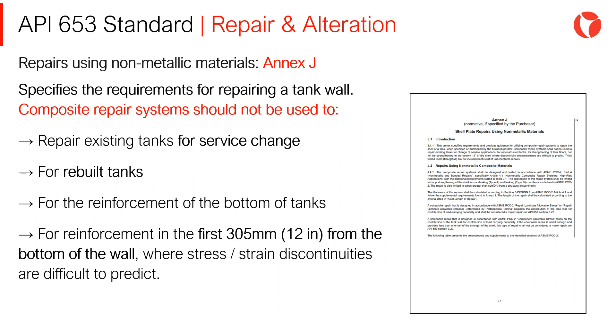Annex J specifies the requirements for repairing a tank wall. Composite repair systems should not be used to repair existing tanks for service change, rebuild tanks, or for reinforcement in the first 305 mm (12 inches) from the bottom of the wall.